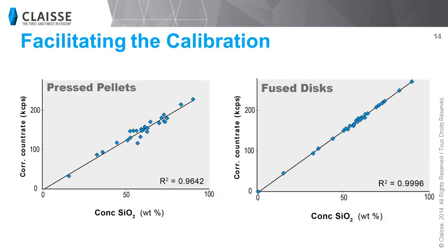Using fusion makes the calibration easier. As you can see on the first graph, the particle size and mineralogic effects lead to calibration spread and to poor accuracy if you compare it to a calibration curve made with fused glass disc. As a matter of fact, the calibration is no longer limited. It can be applied to a larger range of composition. The calibration can also be made with synthetic standards, and it allows the application of matrix correction where it was previously not applicable.